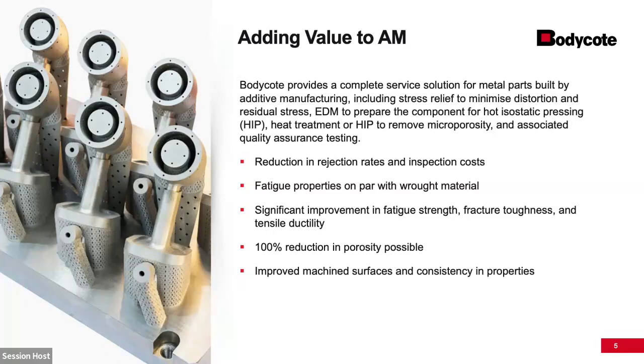So the value add is a reduction in rejection rates and inspection costs. Fatigue properties are on par with wrought material. Significant improvement in fatigue strength, fracture toughness, and tensile ductility. 100% reduction in porosity is possible, and improved machined surfaces with consistency in properties.